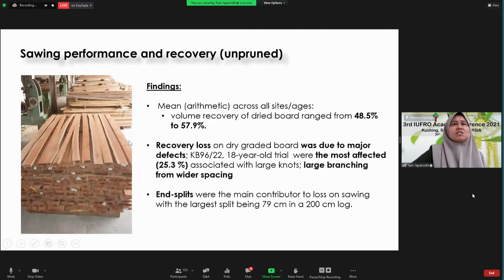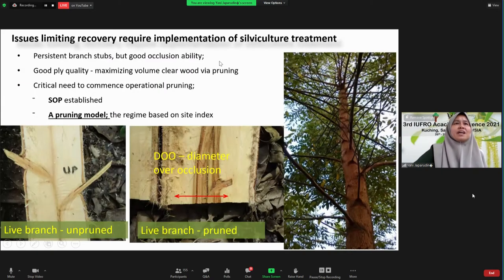Okay. But the sawing performance, this is the recovery that we get. And again, recovery loss on dry grade was due to major defects because of the large branch associated with wider spacing. And then again, end splits is the major contributor. So there is an issue limiting recovery, requiring implementation of silviculture treatment. And there is a critical need to commence pruning.